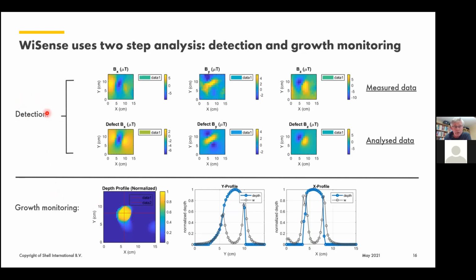First, the detection algorithm is doing its work. It is comparing in the top row the measured magnetic fields with these templates and trying to optimize the match with the template. And that shows the direction of the dipole. You can see there's a slight angle in the dipole. It's picking that up, also the size and the magnitude of the field.